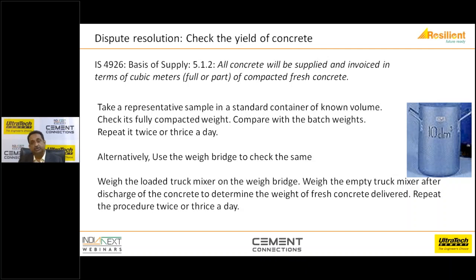Another alternative is to use a weighbridge. You can drive the truck mixer onto the weighbridge, check the weight of the concrete, empty it, and then take the weight again, so you know exactly how much weight has gone, and as per the delivery challan, what the volume is. You can repeat this to ensure that you get the right yield. So this is one way of checking the yield and trying to find a resolution to this dispute of short measure.